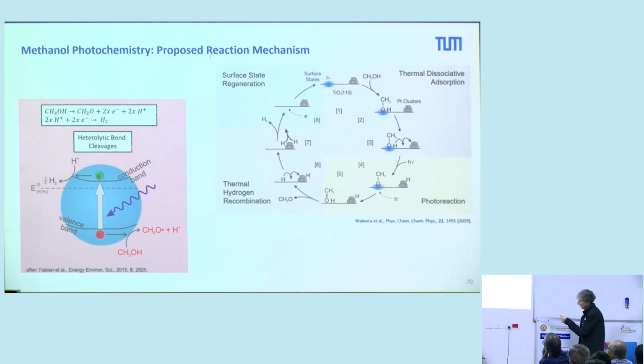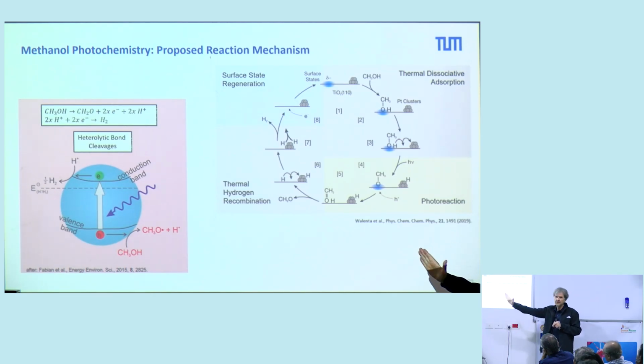Then, of course, upon adsorption, you produce a first hydrogen on the surface. The oxidation produces a second hydrogen on the surface. And we showed that you have a migration of this hydrogen to the cluster, and a thermal recombination of hydrogen on the cluster, and you're producing H2. That means we only need one photon. It is not in line with this picture where we would use 2 photons.